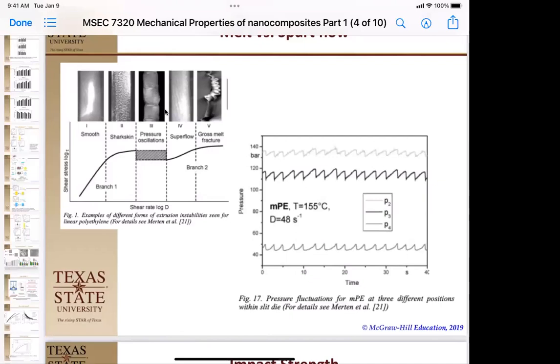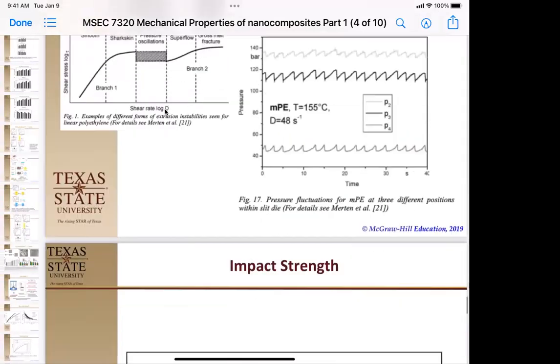So what they probably need is to change the blades so there's more shear running at a lower temperature, so that they can get it to stay in this nice sharkskin or smooth mode. You want to have that better flow with a higher shear. Apparently, this little bit of extra shear in the systems will give them a better dispersion. So I thought that was kind of an interesting way to do it as well. Okay.